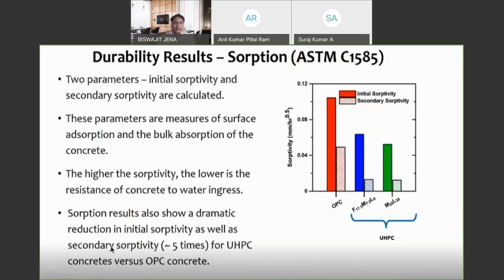We will see that the initial sorptivity is governed by the larger pores, which can absorb a lot of water early on. The long term sorptivity is also governed by some amount of diffusion, through the smaller pores in the material, and it is not completely diffusion. You have probably not transitioned into completely diffusion controlled behavior, but it will give a fair indication of the size of the smaller pores of the material also, and you can see the secondary sorptivity is much lower.